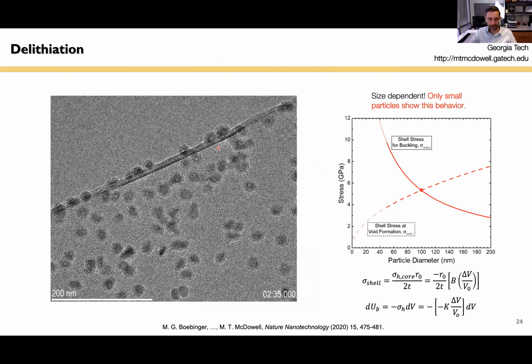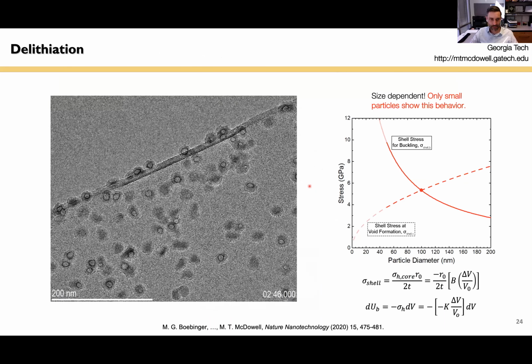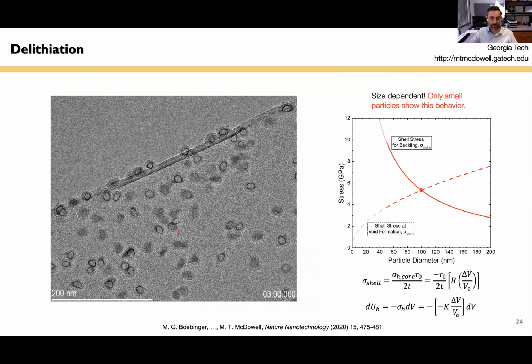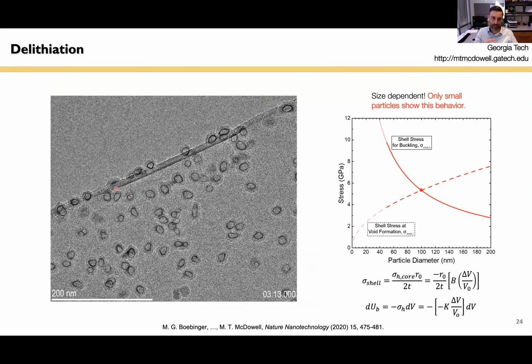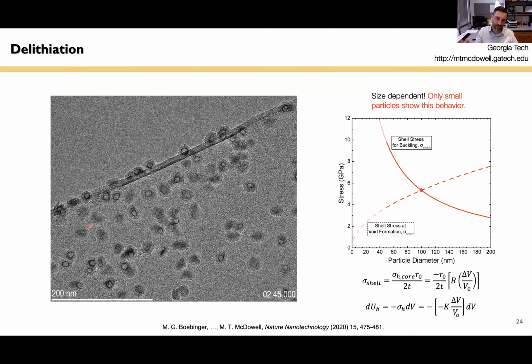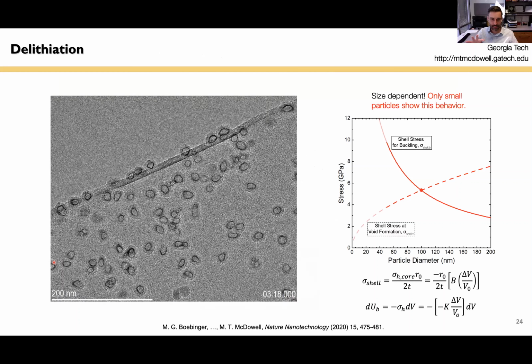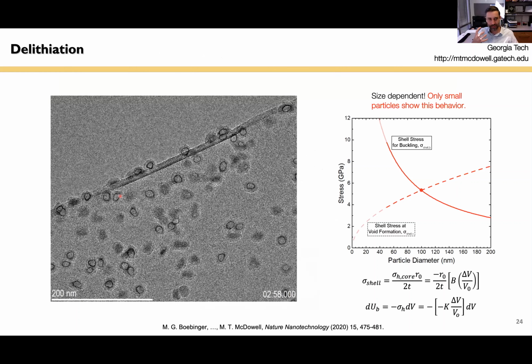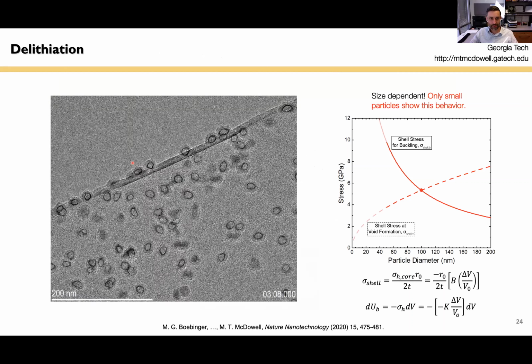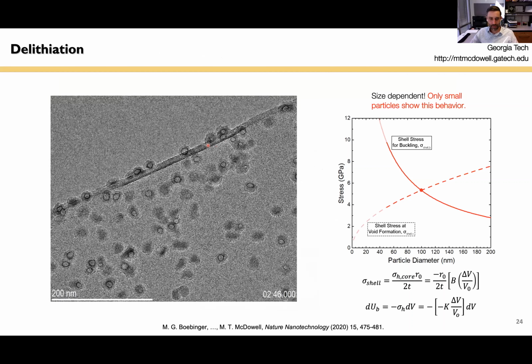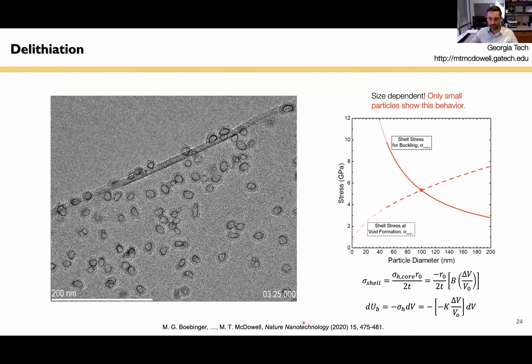So I want to just show the video here of this delithiation process. These are these lithiated nanocrystals undergoing lithium extraction. So lithium is leaving. You can't see the lithium leaving. What you see is the antimony shrinking and forming these hollow structures surrounded by the oxide shells. And so this paper, we're pretty proud of this paper. If you're interested, you can check this out.